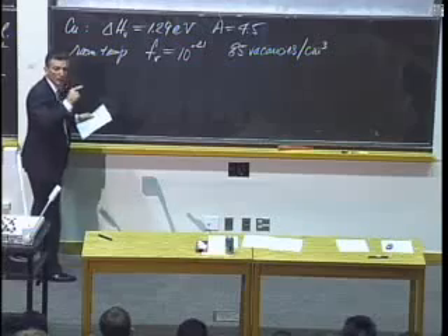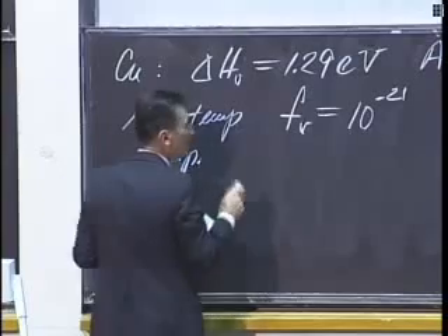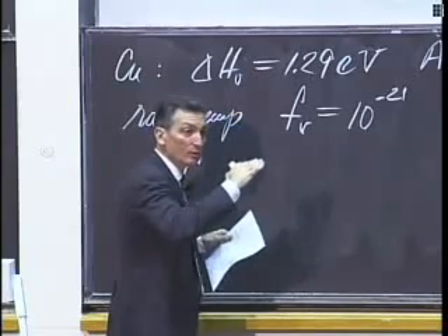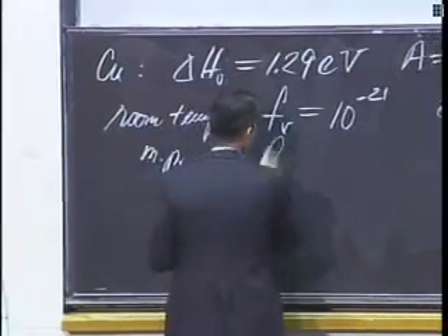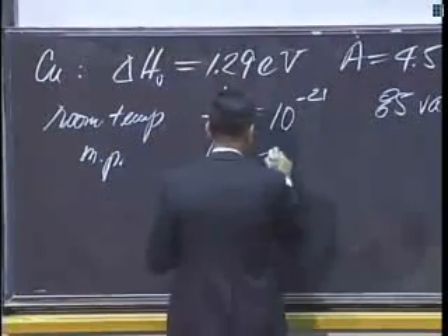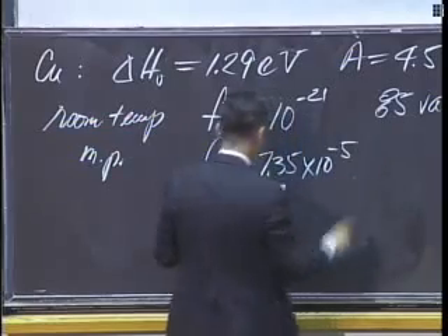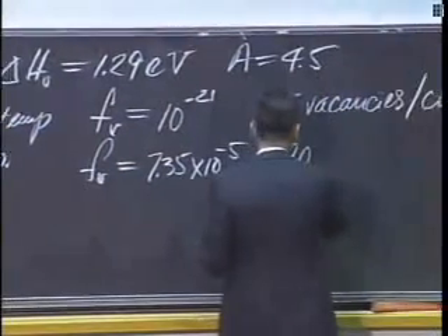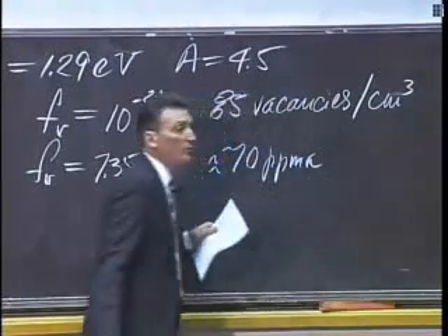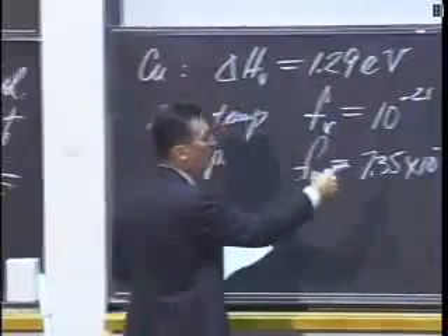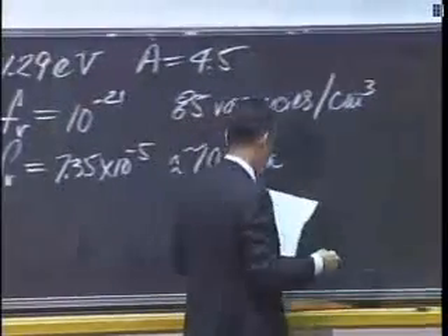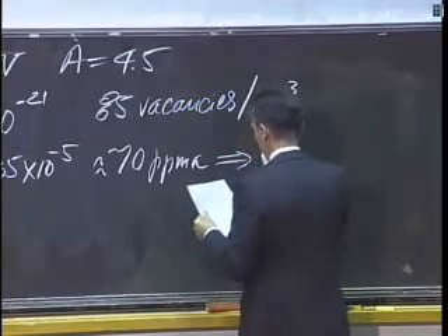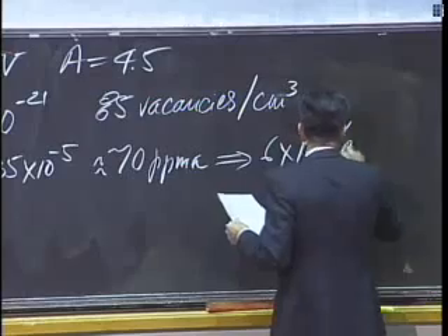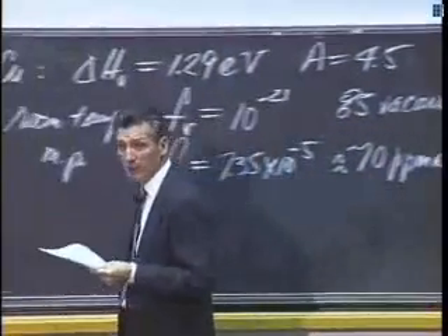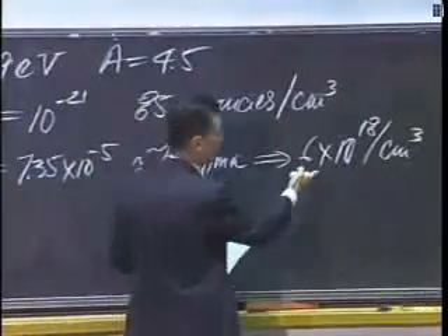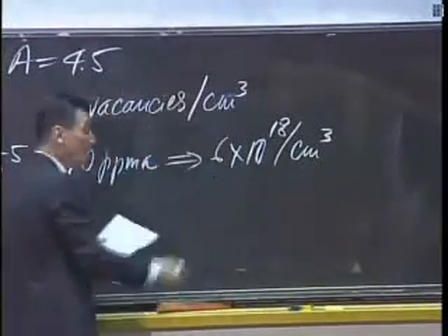And then I said, well, what happens if we go to the melting point? At the melting point of copper, I'm not going to melt the copper. It's like ice at 0 degrees C. It's copper at the threshold of melting, but still solid. If you do the calculation at the melting point of copper, you get 7.35 times 10 to the minus 5, which now turns out to be about 70 parts per million on an atom basis. So for every million copper sites, you can expect about 70 of them to be unoccupied. So now we're starting to get up to real numbers, because that would give us a vacancy population of 6 times 10 to the 18th per cubic centimeter. That's substantial. This is the kind of stuff that would be perceptible if this was a dopant. If this were a dopant concentration, this would alter the electrical properties of silicon.